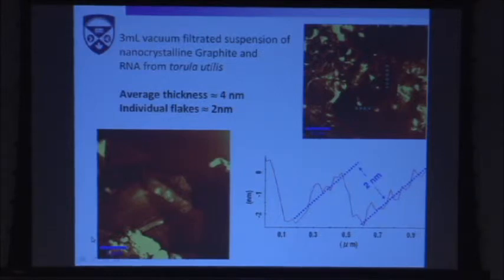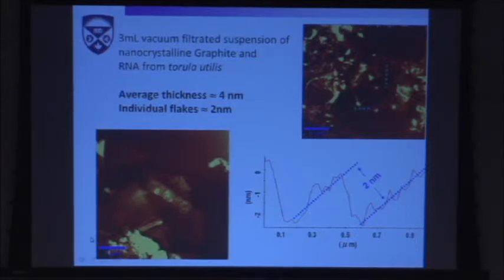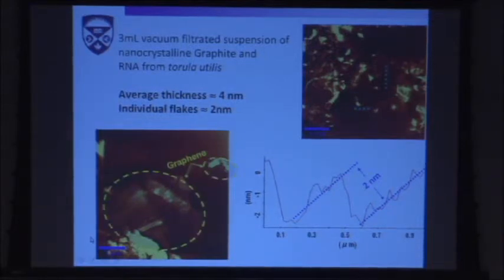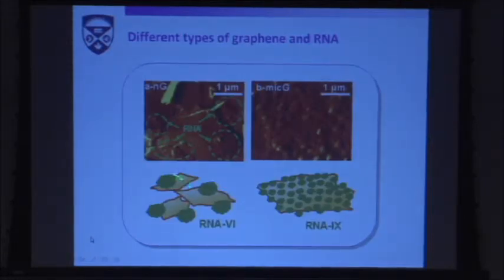Of course, the type of RNA and the ability of this RNA to disentangle in water and penetrate in graphite is pretty important. I won't comment too much on the types of RNA that you use. Also, the defects on the graphite that you are using are pretty important. And you have regions of these films where you have graphene, regions where you have RNA. So they're really graphene-RNA nanocomposites, in principle, that are very different depending on the type of RNA I'm using